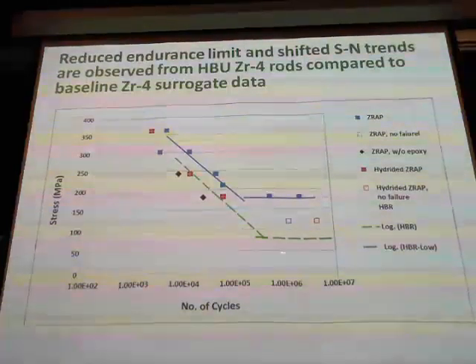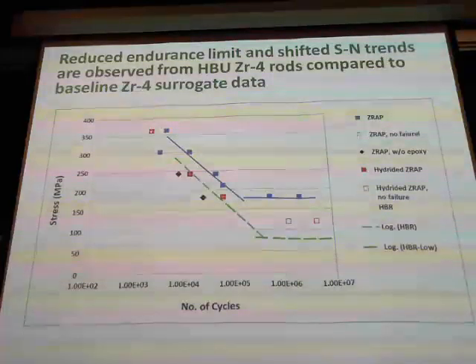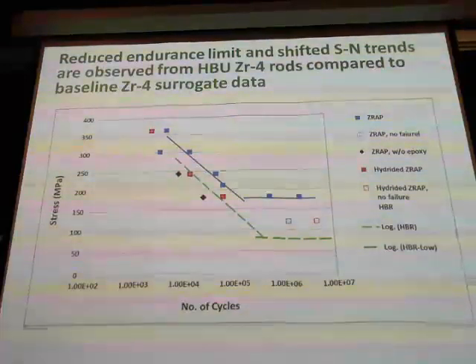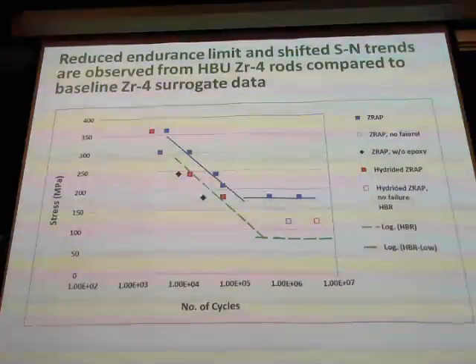And we found out that actually the green one was irradiated. This one here is H.B. Robinson. And with the pre-hydride, you can dictate the hydride content. You can mimic the irradiation property. This is in the infant state. Now, if this can be proven to work, you can do it not in a hot cell, you can do it here.